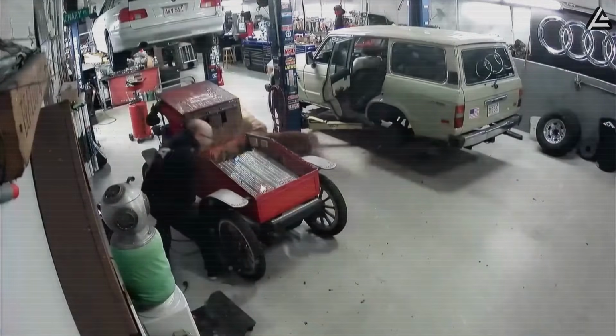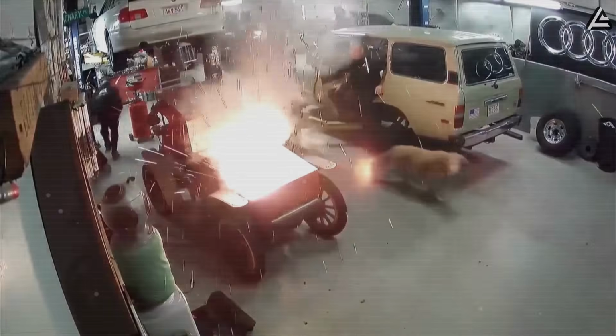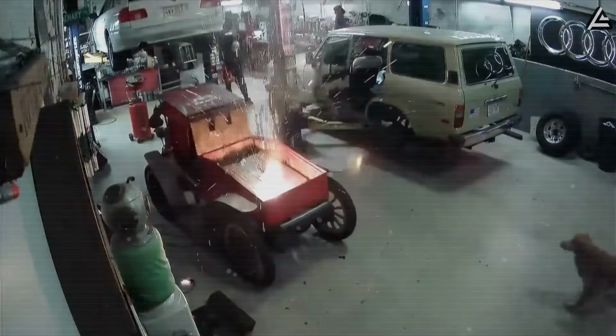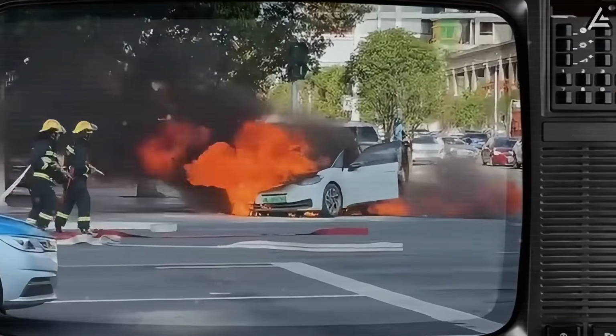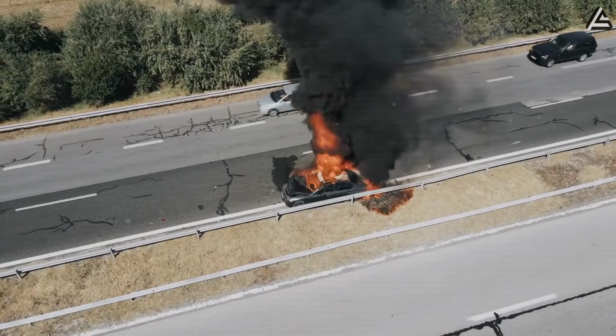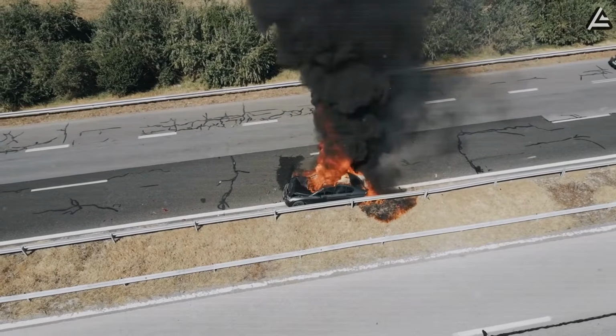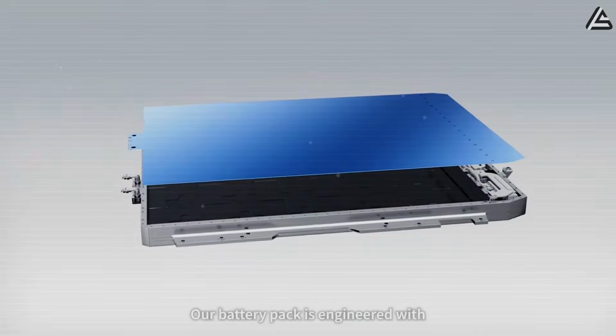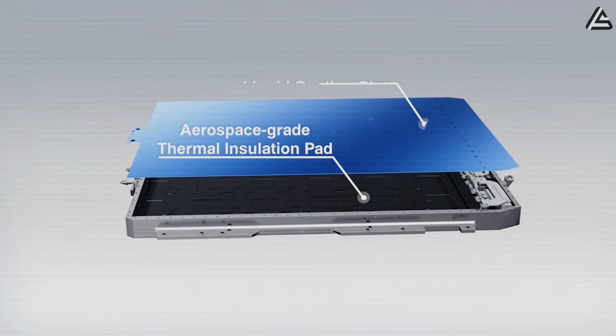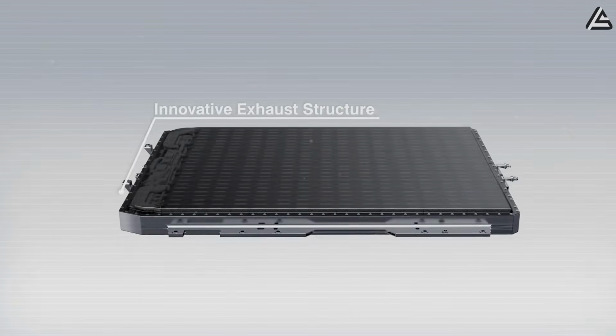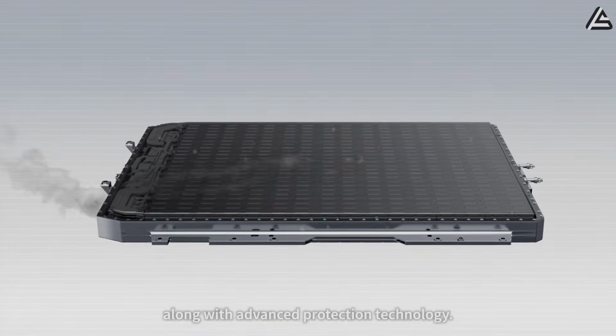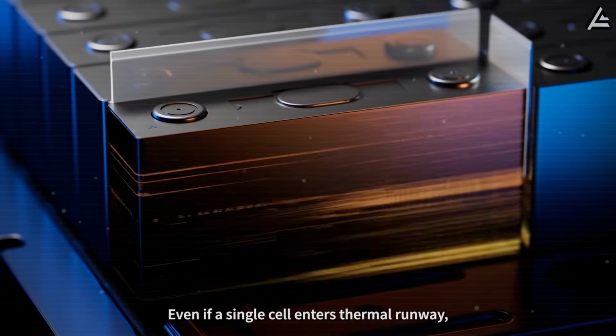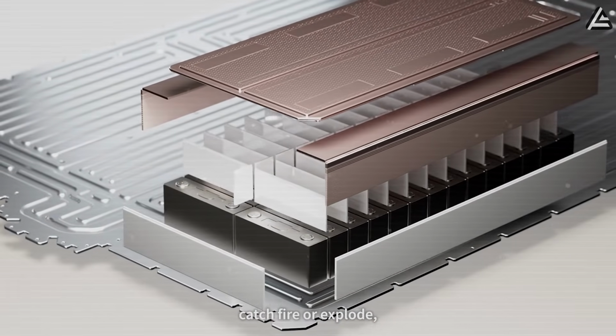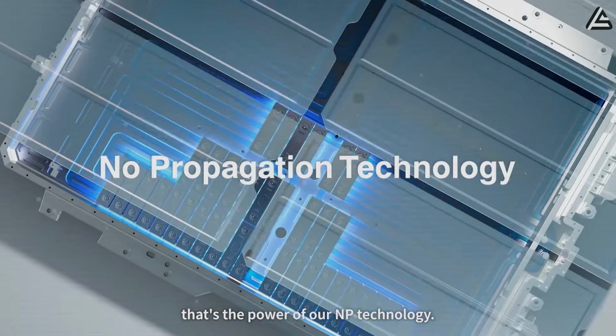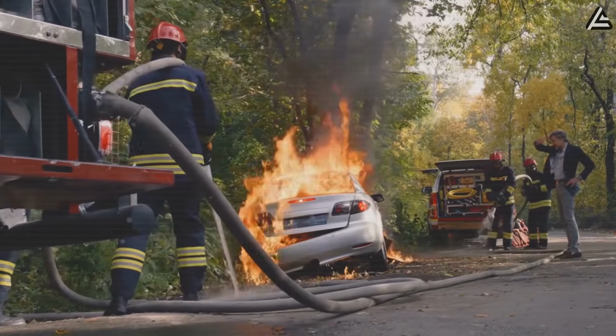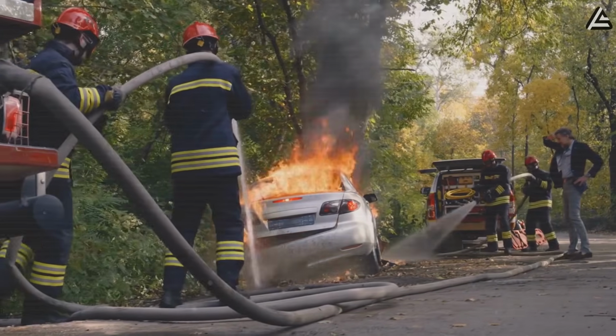When a lithium-ion cell ruptures, the electrolyte decomposition liberates oxygen, which feeds the fire. That's why EV fires tend to burn until every reactive element is consumed, often reaching flame lengths of several meters and lasting for hours. Aluminum ion does not share this self-oxidizing characteristic. Even if a short circuit triggers localized heating, the reaction is expected to die out rather than perpetuate itself. For first responders, this could mean the difference between deploying 20,000 gallons of water versus a few hundred, closer to the needs of a gasoline vehicle fire.